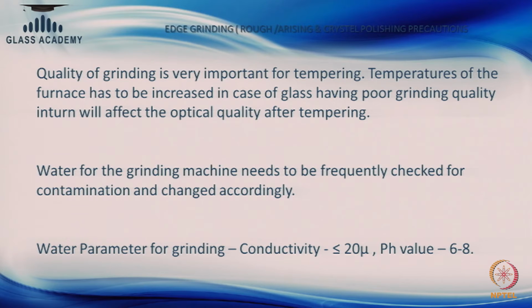Quality of grinding is very important for tempering. Temperature of the furnace has to be increased in case of glass having poor grinding quality, which in turn will affect the optical quality after tempering. Water for the grinding machine needs to be frequently checked for contamination and changed accordingly. Water parameters for grinding: conductivity less than or equal to 20 microsiemens, pH value 6 to 8.